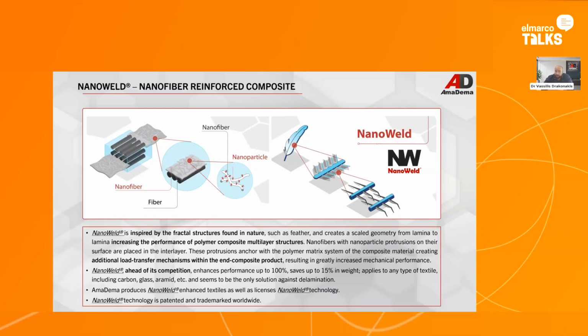This is a patented technology, and depending on the nanofiber type, on the nanofiber material, and the combination with the nanoparticles, it can increase mechanical performance up to 100%. And the mechanical performance can mean different properties, I will explain later, which can be tensile properties or bending properties or fracture toughness properties.